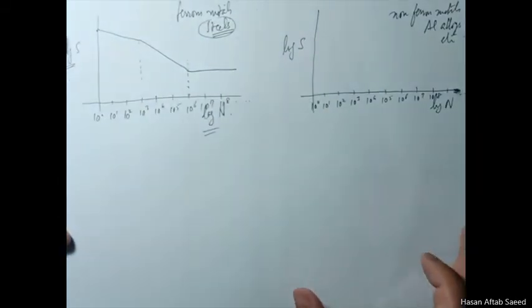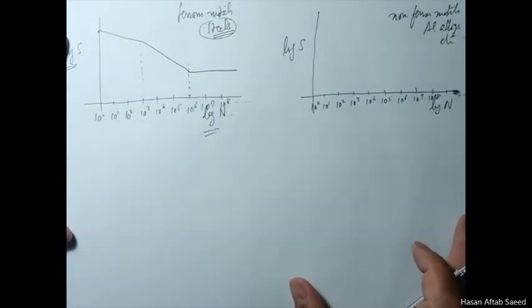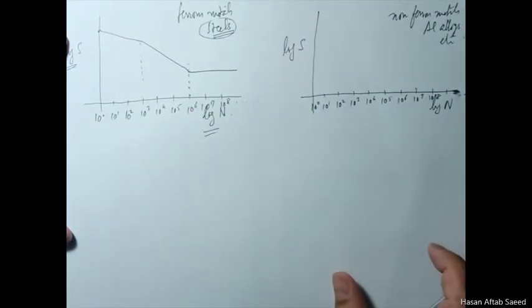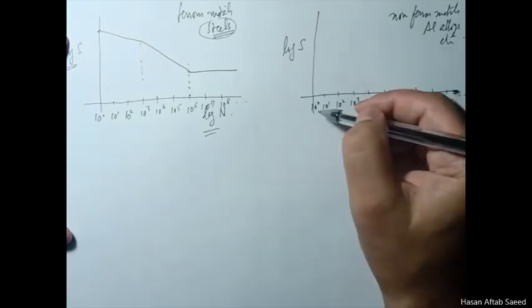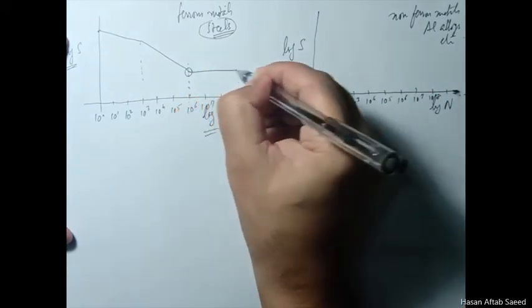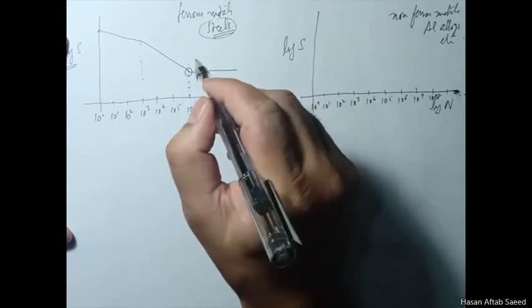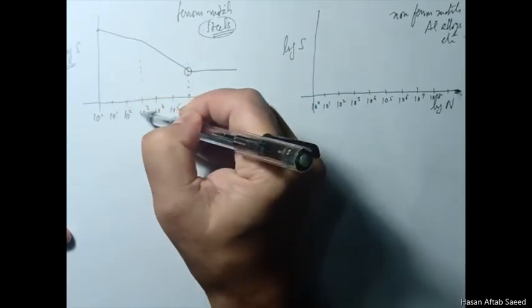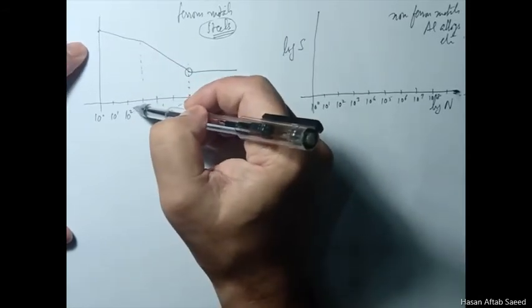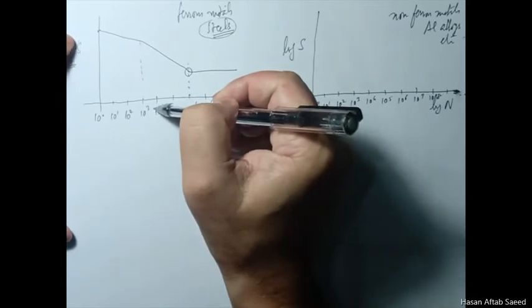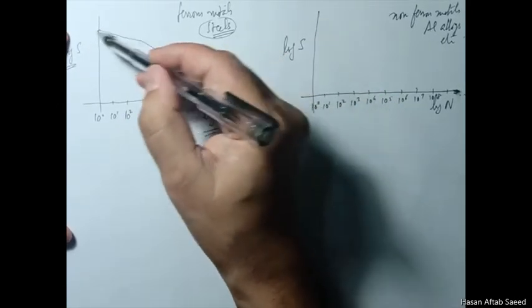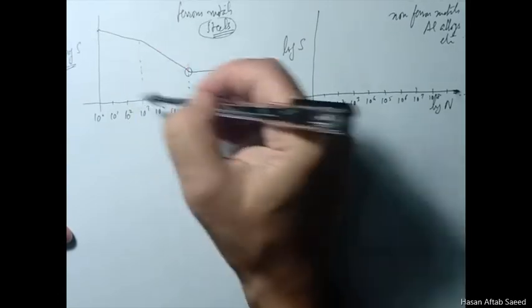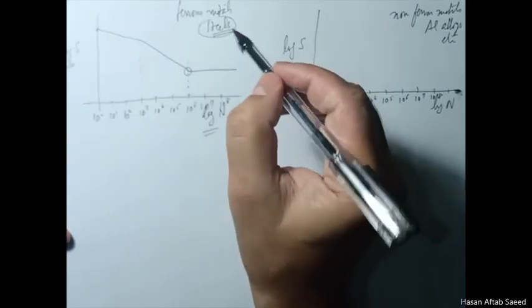I'll discuss this later on because there is a lot of detail about this. There's a knee here, and after this it straightens. What it tells us is that as you keep on increasing the stress levels, the number of revolutions before breakage occurs becomes lower and lower, which makes sense. Obviously this detail we wouldn't have known, but we know that as this increases, this should decrease. But a strange thing happens.